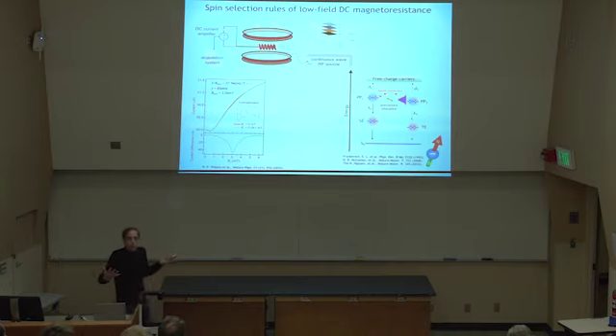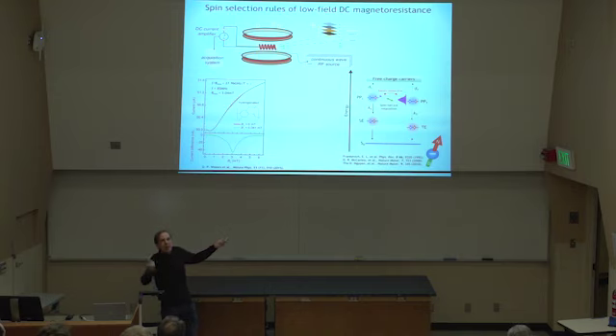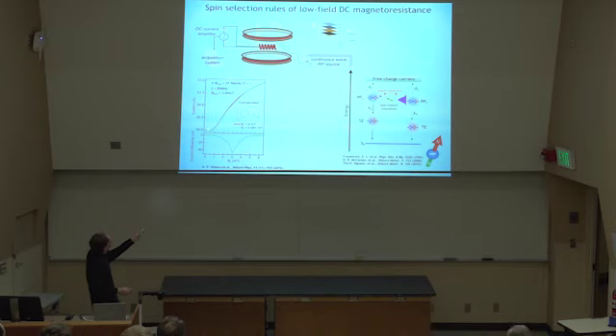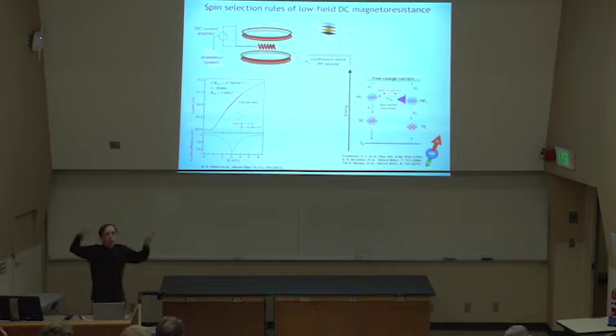And again, in absence of polarization, there's no thermal polarization. Again, what you do is you carry out magnetic resonance transitions between permutation symmetry states. Now, why is this so weak? If external magnetic fields change rates and magnetic resonance does the same, why is that change so weak? Because these lines are so wide, and these lines are so wide because they are governed by the local random distribution of hyperfine fields, the proton-induced local magnetic fields. And because of that, if I apply, let's say, 4 millitesla here, and then I have magnetic resonance with pairs that correspond to this signal, then I only address a small subensemble that corresponds to these 4 millitesla. And that's a small fraction of the overall ensemble of charge carriers.